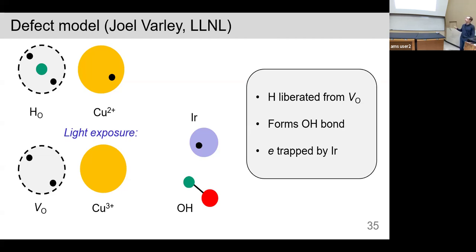So just to summarize, when we expose it to light, hydrogen is liberated from the vacancy, forms an OH bond, and that is metastable at room temperature. But the electron, instead of producing PPC, conductivity, the electron gets trapped by the iridium. So we do not get conductivity thanks to the iridium.